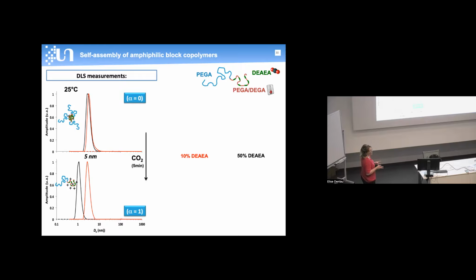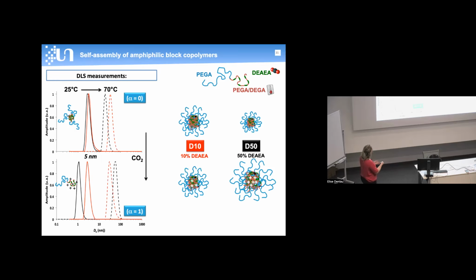So for us, 5 nanometers is a typical size for a single unimer chain in solution. And when the aggregates are formed, the size really increases up to something around 50 nanometers. And it was the same for the other system, also around 5 nanometers for a single unimer chain, and 50 nanometers for the aggregates.